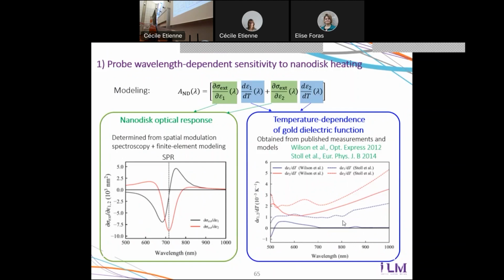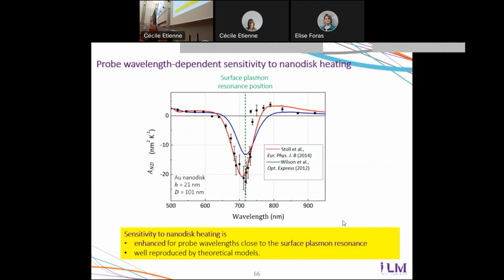Regarding the sensitivity to heating, it's something that we can model. To do that, we need to know how the dielectric function of gold depends on temperature. It's something that was known from previous experiments and previous models. And we need also to know how the optical response is affected by a change of refractive index, something that we can know from optical calculations. So once we have this, we have simulated the sensitivity to heating, which depends on wavelengths.